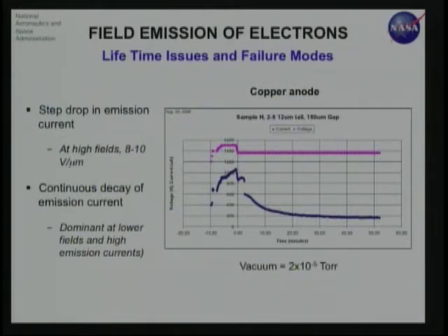And you do a lifetime test, unless you do certain modifications to the sample, you won't be able to use them, because there are two ways in which these field emitters fail. One is they have a gradual decay, that happens because of the tips burning slowly while under field influence, and also the sputtering of the anode material that falls on the field emitters and masks the tips that are emitting. So you have an issue of constant decay.